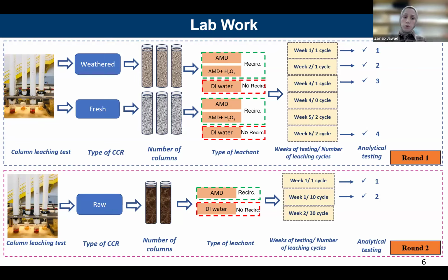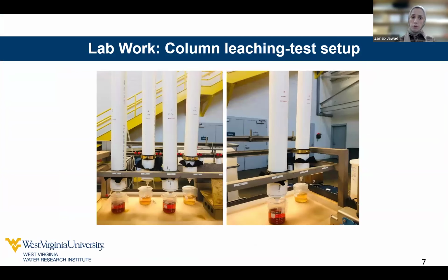During the second round, we used the raw refuse, and we modified this round based on the results of the first round. We used the acid mine drainage and DI water as leaching solutions. The idea here was to leach as frequently as possible, so that once the discharge from one cycle stopped, we started the following cycle. But then we decided to terminate this test after receiving the results of the 10th leaching cycle, and we will know why in the results in a little bit. So this is the setup of the column leaching test that we did in the lab.